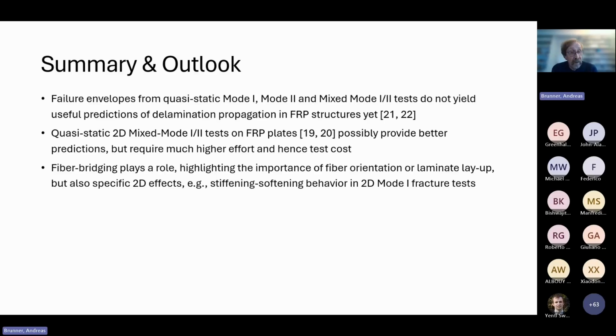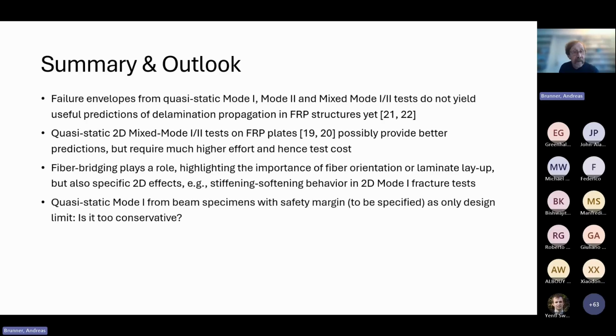There are two things that play a major role, and this has already been mentioned before as well. Fiber bridging plays a role, and that highlights the importance of the fiber orientation or the laminate layup. But as I also tried to point out, there are specific effects that you will not see in 1D beam specimens, but you need really 2D specimens, like this stiffening, softening behavior in the mode 1 test. Now the question is, if we reduce the test effort to mode 1 from beam specimens, which are easy to do, with a safety margin that would have to be specified in design codes, for example, of course we run the risk that it could be too conservative, which means we will give away some of the potential that the material has.